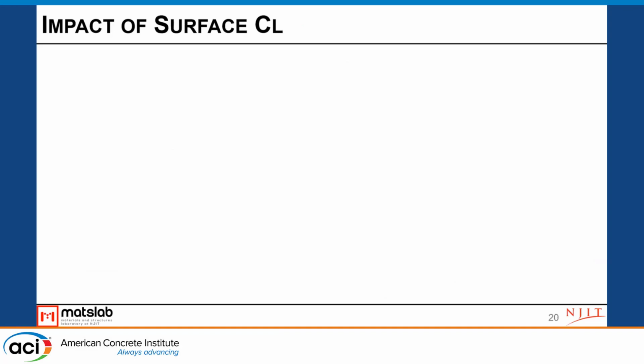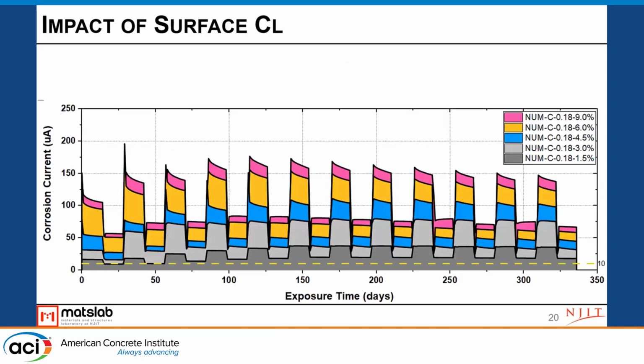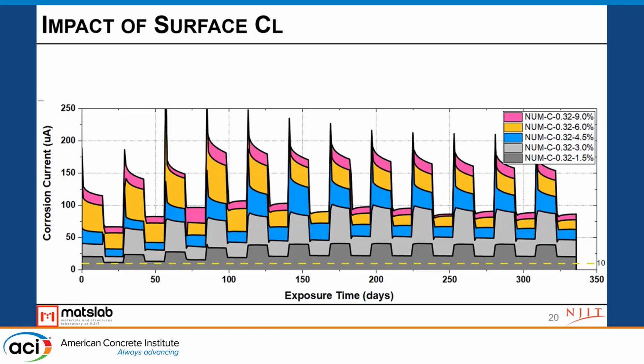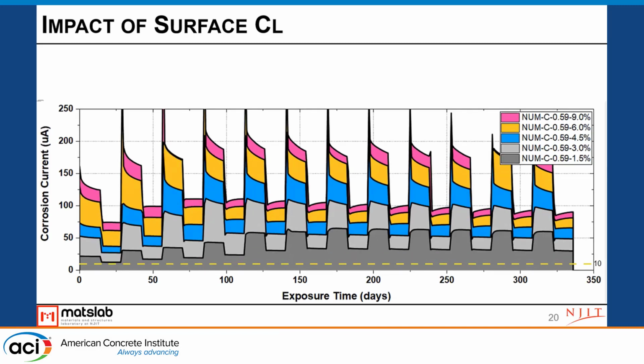Now we want to look into another factor, which is surface chloride concentration. So when we plot the different chloride concentration conditions under the same crack width, we see from 1.5 to 4.5 surface concentration, the corrosion current is increasing almost proportionally. However, when we get higher chloride concentration at the surface, again it slows down, and the gap between these different concentrations, especially at higher concentrations, is getting smaller. And the same trend is observed with the 0.32 millimeter crack width, and also 0.59 millimeter crack width.